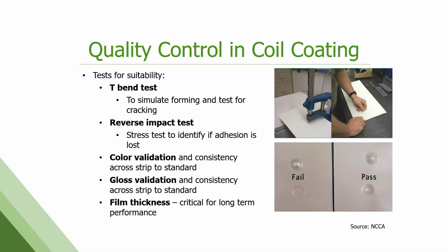The quality control through this process is quite rigorous. As you can imagine, like I said, these paints and substrates have to go through a lot of handling and forming after the fact. So the paint companies do a lot of rigorous quality control on the paints. We do a lot of rigorous quality control on the finished product once the coil is painted. We've listed here some of the more critical ones. The T-bend test, this is where we actually fold the metal back on itself very tightly, and we look to see if the substrate or the paint is cracking or opening. We do a reverse impact test where we drop a hard, sharp weight on the surface to make sure that the paint adheres and there's no cracking or delamination.